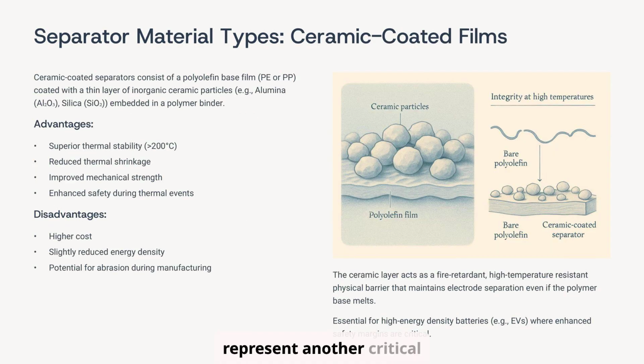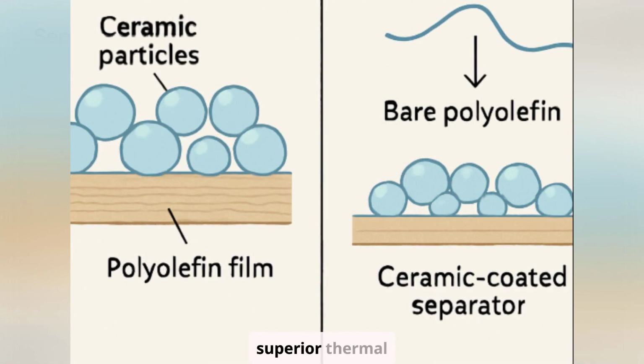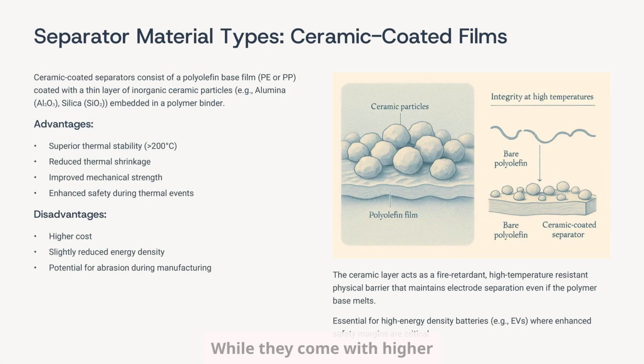Ceramic-coated films represent another critical separator type. These consist of a polyolefin-based film coated with a thin layer of inorganic ceramic particles, such as alumina or silica, embedded in a polymer binder. Advantages include superior thermal stability, often exceeding 200 degrees Celsius, reduced thermal shrinkage, improved mechanical strength, and enhanced safety during thermal events. While they come with higher costs and a slight reduction in energy density, the ceramic layer acts as a fire retardant, high-temperature resistant barrier, crucial for high-energy density batteries in applications like electric vehicles.